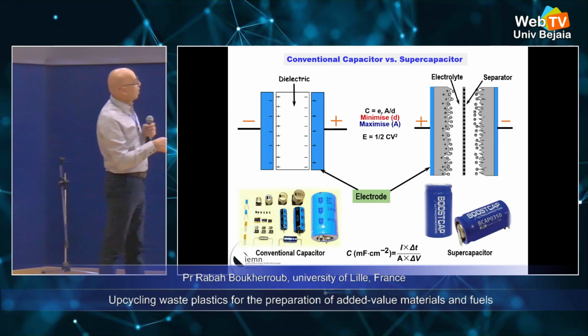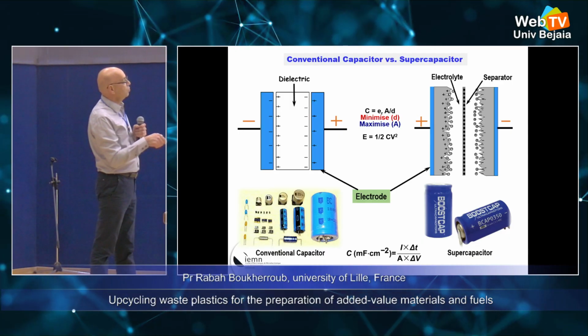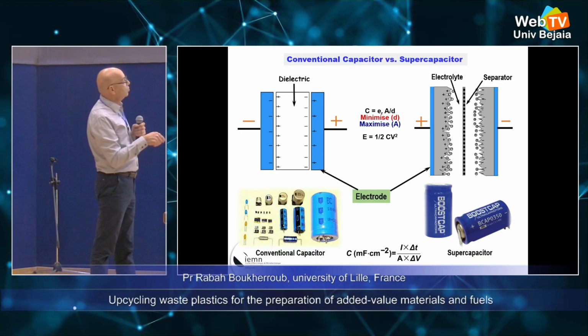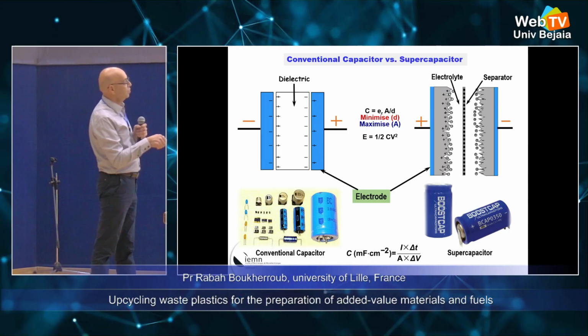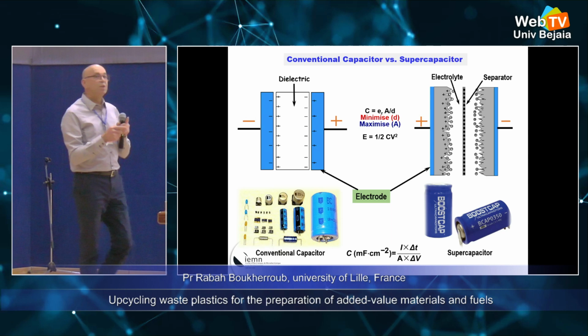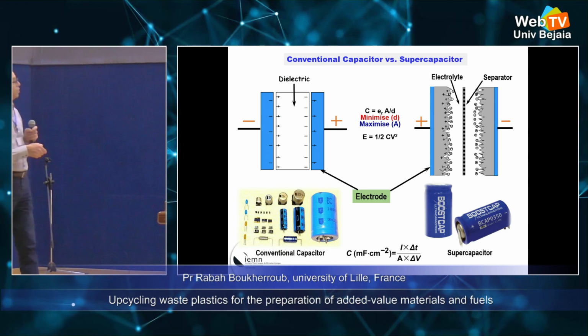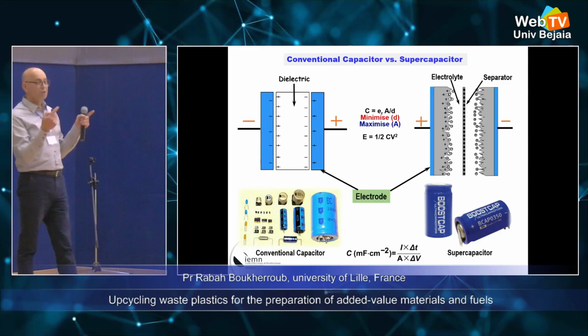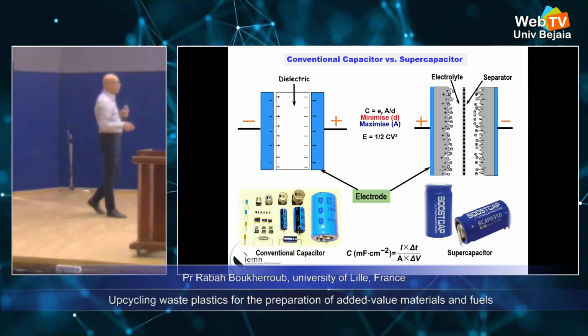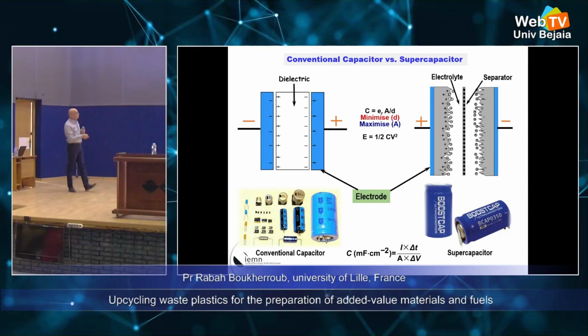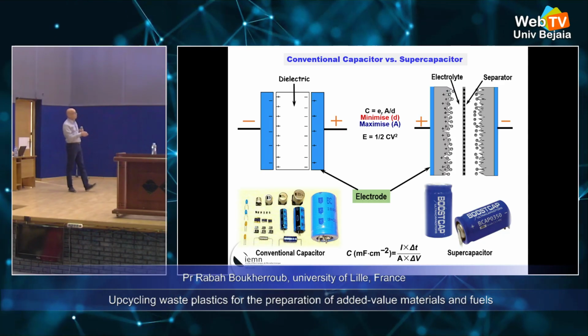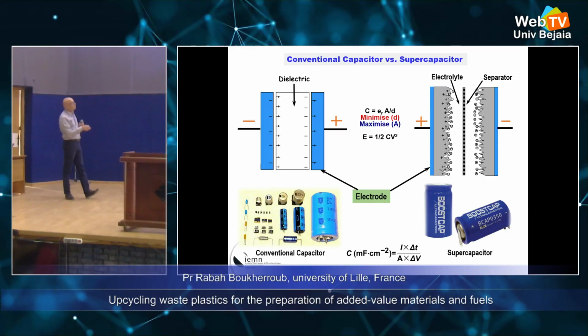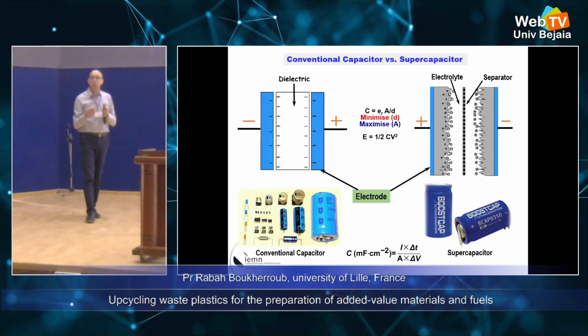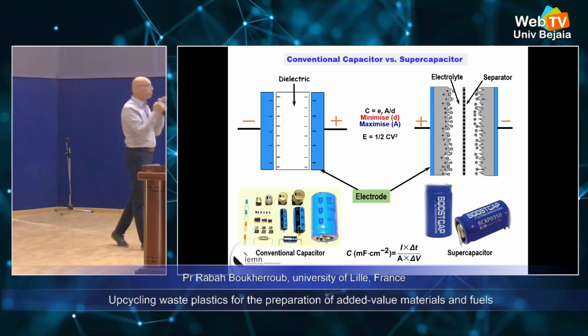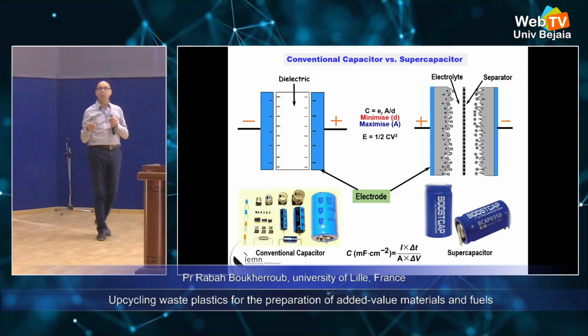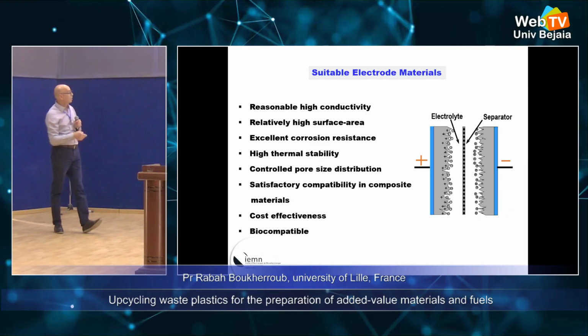When you look now at how you can do this to make a supercapacitor, you have indeed to enhance the capacitance through the surface area, but also the applied voltage. So if you increase the voltage and the capacitance, then of course you enhance the energy storage of the material. The way to do it, you make new materials as electrode, but also you play with what you call the electrolyte. Instead of using water, you're limited to 1.23 volt. You can use organic or polymer-based or gel electrolytes.